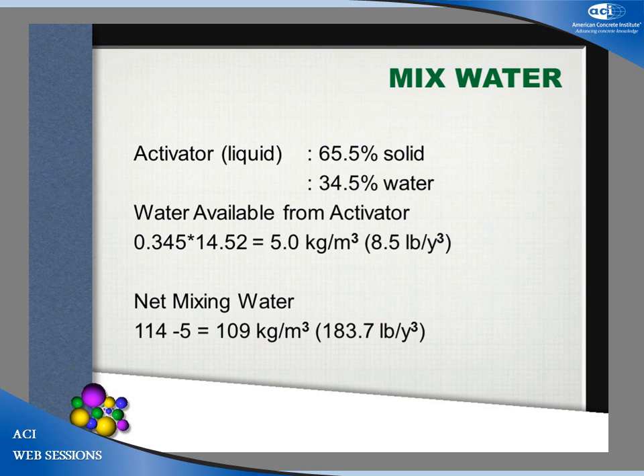Now, our activator has a 34.5% water content. So that water content we need to discount from the water we got. The activator water is 5 kg per cubic meter. So the total water we earlier got is 114. So the net water would be 109 kg per cubic meter or 183.7 pound per cubic yard.